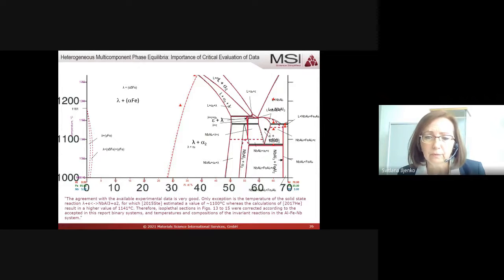And here the conflict was about the temperature of this invariant reaction. And for the rest, the agreement between calculated and experimental phase diagram is very good, but only in this area the disagreement is very large. It's almost 100 degrees, or 50 degrees, 70 degrees. And here the preference was given to the experimental data, which were considered as more reliable. And therefore, in red, you see the phase diagram, which in this area was amended by our authors. All this is well described in the text and the user can follow why these changes have been made.